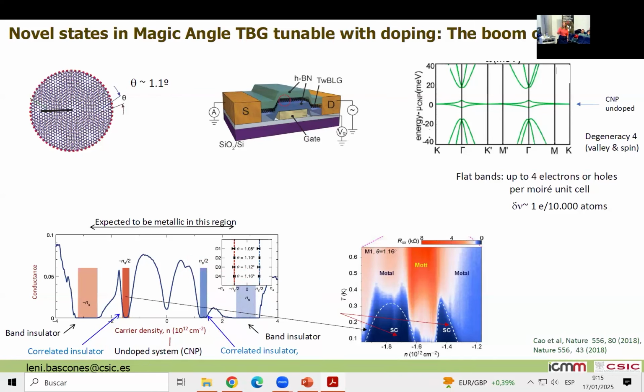But the new thing is that he saw that when he had filling -2 and 2, where you expect that the system is metallic, he found insulators. So what this is telling us is that these insulating states are really caused by the electronic correlation. And he also found an even bigger surprise. Well, that was already quite a surprise, but the other surprise is that there was superconductivity very close to these insulating states. So, well, this was really amazing.